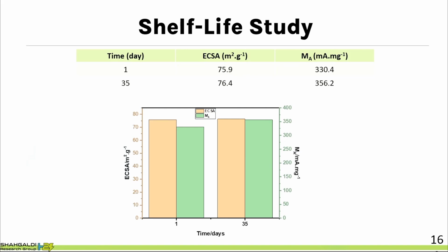The other important thing that we are doing in our lab is a shelf life study. That is also important because imagine that you're in industry and you're making 2 kilograms of platinum carbon or iridium-based material, and you need to put it aside for any reason before you coat your sample. So what is the shelf life? Do you have the same coatability? Do you have the same activity or not? So the shelf life study is also something we do in our lab after screening of the catalyst, in order to make sure the catalyst stays as good as the first day, or to see how many days we can keep the catalyst with the same activity and mass activity.